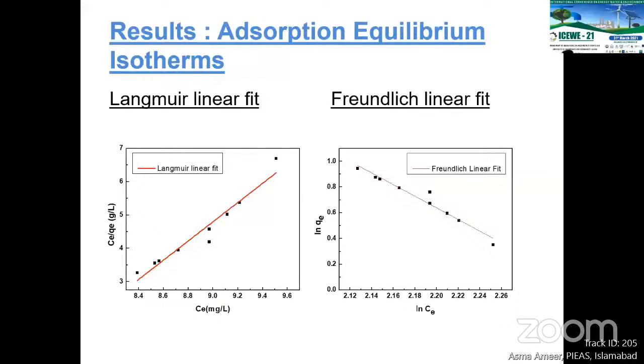Next are the adsorption equilibrium isotherms. Basically, the adsorption isotherms tell about the mode of adsorption, like monolayer or multi-layer formation, and the homogeneity of sites, and it was well fitted by the Langmuir linear fit. And what does it mean? That Langmuir linear fit means that monolayer formation of lead ions on alumina will occur. And it also tells about the homogeneity of sites, meaning all the sites of alumina are equally accessible for lead ions.